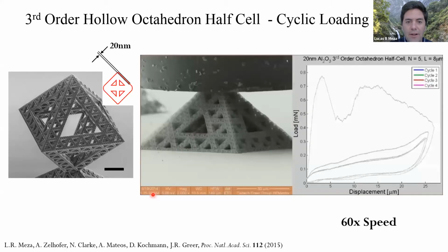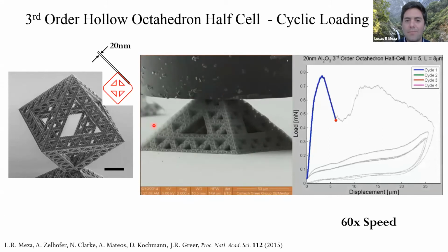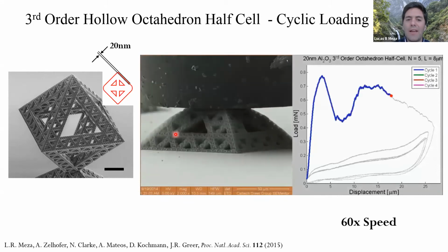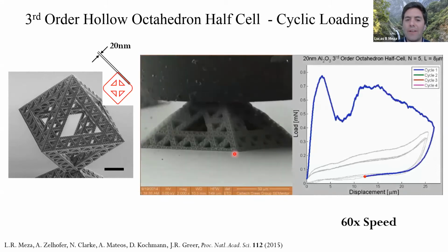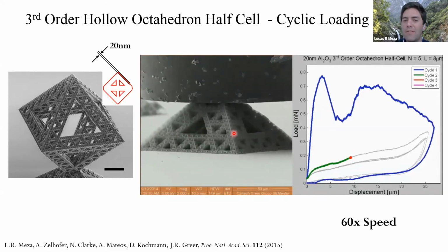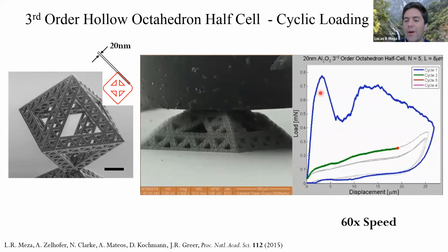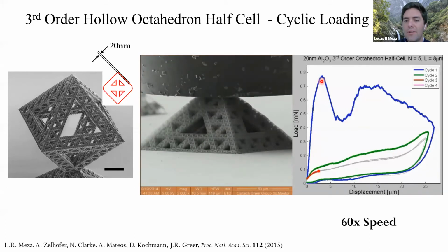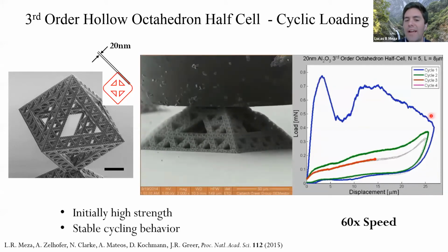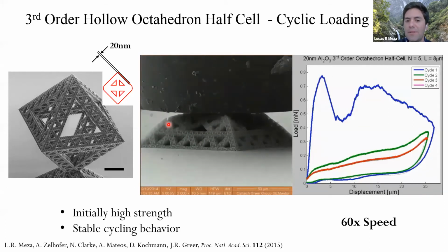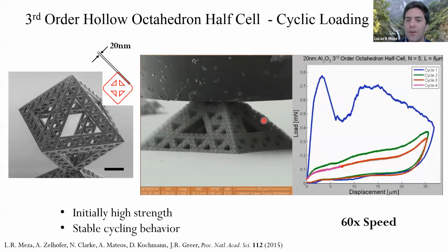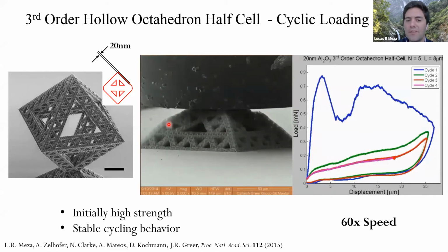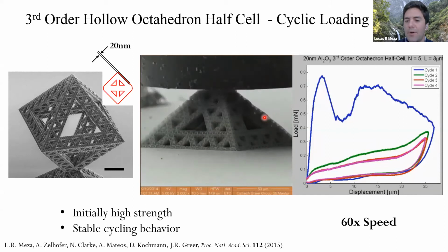Here I'm going to show you cyclic compression on a third order half cell. Basically what we were looking for was how this hierarchy in a single beam changed behavior. Here you had a stiff, strong initial loading cycle. After that, you can actually see some of these cracks and voids starting to open up — especially here and here, cracked parts of the beam.